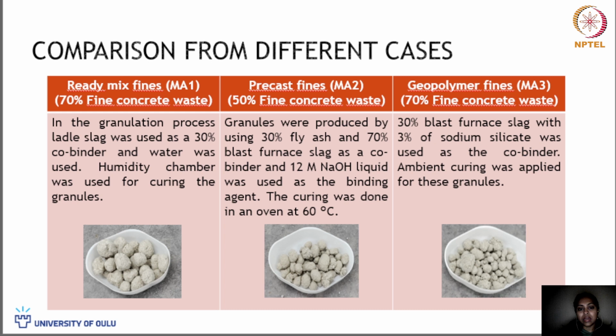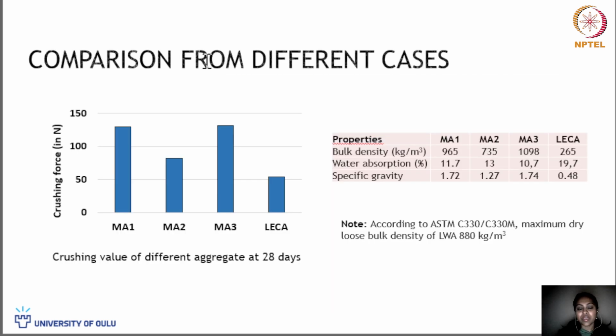So by using life cycle analysis, we try to understand what kind of impact we created in these materials. You see, when we compared different cases with the available commercial aggregate, in most cases the crushing forces are higher than the commercial aggregate. However, the density also was way higher compared to the commercial aggregate. So the water absorption reduced and the specific gravity is higher. However, according to the ASTM standards, the maximum dry loose bulk density for a lightweight aggregate is 880 kg per meter cube, and we could produce one of the aggregates in that range, that is MA2 with the precast fines with 50% of this recycled fine material.